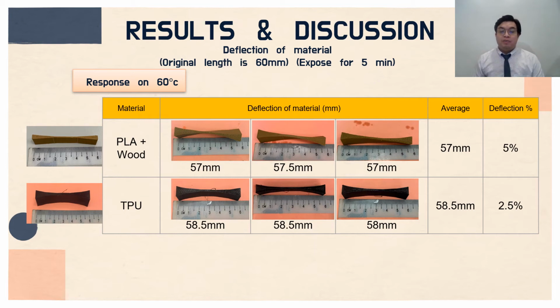The deflection of the material has been recorded after the heat was applied. The heat is applied for 5 minutes. As you can see on the left side, there is the original size of the material before being placed into the heat. As you can see, the average reduction is 57 mm and 58.5 mm for the response at 60 degrees Celsius. This shows 5% deflection for PLA plus wood and 2.5% for TPU.